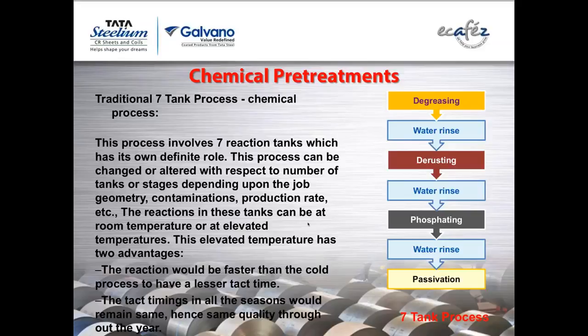After that, again, there is a water rinse. Now, all these water rinses you can have as two rinses instead of one. So the rinsing would be better, and the second tank will always remain within the pH demanded by your chemical suppliers, close to 7. Now, when derusting is removed, the next water tank also gets removed, and what you need is to activate the surface for the phosphating reaction. So one tank is added in that case. In the new lines where derusting is removed, it is called the activation tank, the surface activation tank.